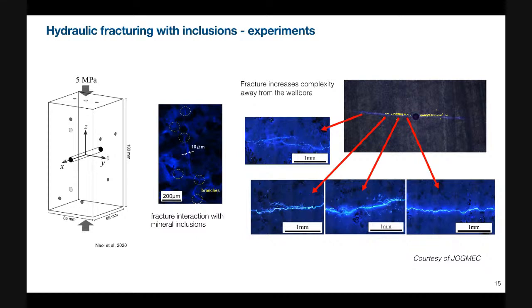So we can consider that those inclusions have the same mechanical properties. But these grains or inclusions seem to have some weak interface, because in this picture you can see that the hydraulic fracture is clearly influenced by the presence of the inclusions. Sometimes cracks branch, and sometimes the crack penetrates the grain. And this picture also shows how the fracture pattern looks.